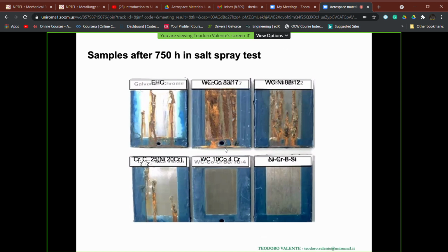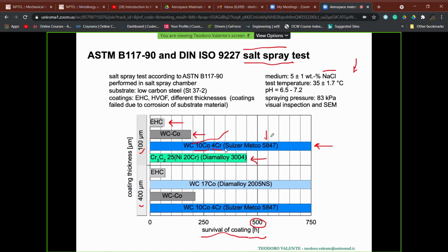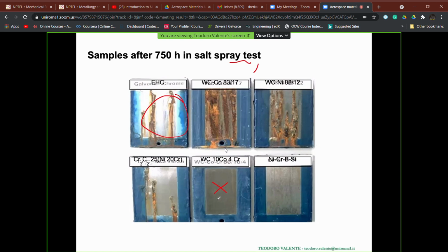These are some examples of the samples which have been tested. You see here rust, which is formed after the salt spray test. Here, different solutions of HVOF coatings. But if you have a look at this, which was the best performing one, with 100 with 400 in this case, together with the powder made only of tungsten carbide and cobalt, which is the powder type listed in the table I left to you before, you can just see that the appearance is very, very different. This is after 750 hours of testing, thus showing the better performance of HVOF.